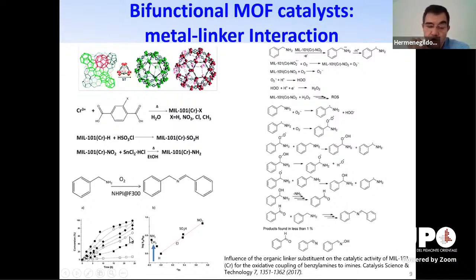And again, when you have different substituents and you plot the Hammett sigma constant against the relative initial reaction rate in logarithm scale, you have a linear line, except when there is a real activity from the substituent. And in this case, again, the amino group has much higher activity. Again, this is a logarithm scale. So this means that we have an activation about 50 times higher due to the presence of the amino group.